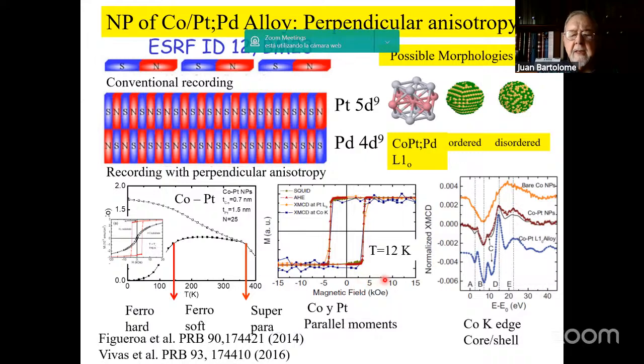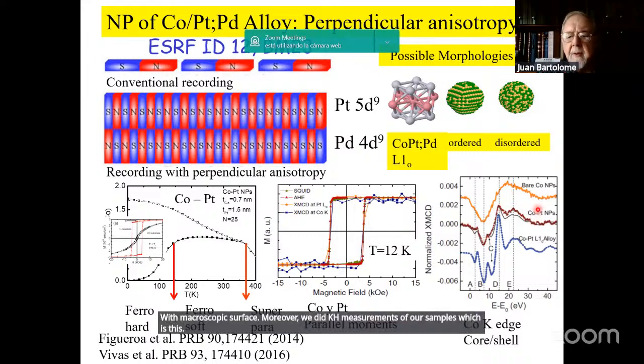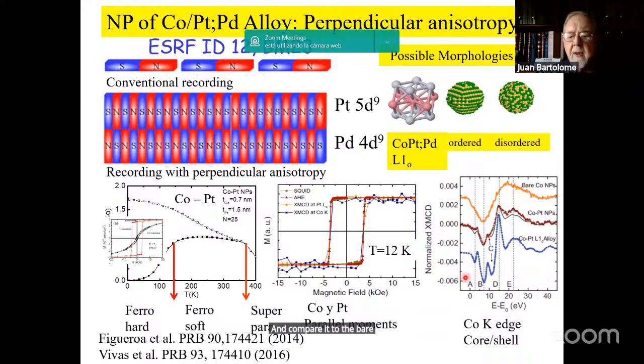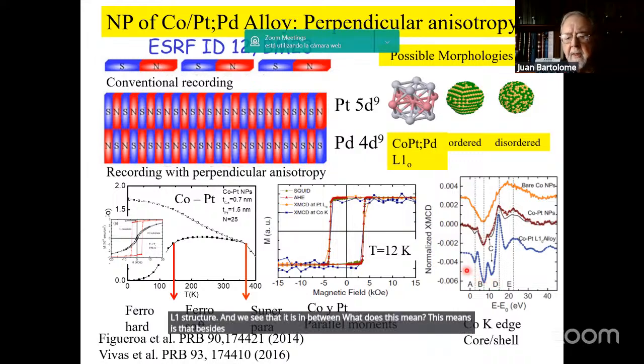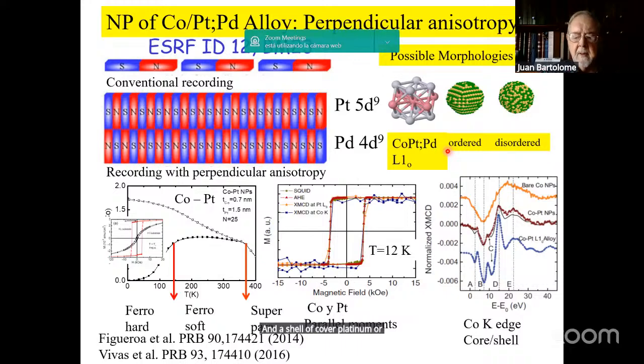Moreover, we did K edge measurements of our samples, which is this, and compared it to the bare cobalt particle or to the cobalt-platinum L10 structure. And we see that it is in between. What does this mean? This means that besides having the cobalt-platinum structure, there is still bare cobalt. So we think that these particles are of the core-shell type: a core of cobalt remaining and a shell of cobalt-platinum or cobalt-palladium material.